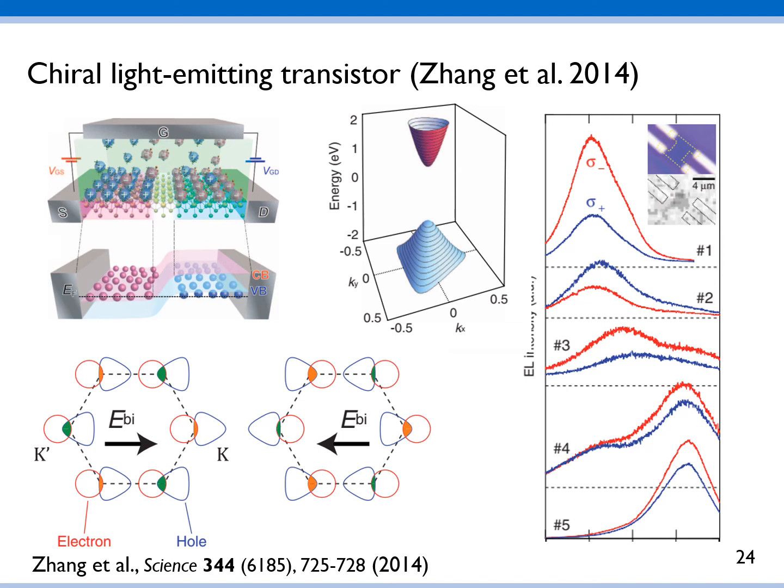But they created a monolayer-like Valley response, in the sense that, through the applied gate voltage, they broke the spatial inversion symmetry, and then through the electric double layer that was applied to the sample, they considerably altered the band structure of the tungsten diselenide to recreate a more or less direct band gap at the K point. And so they could measure those Valley properties.